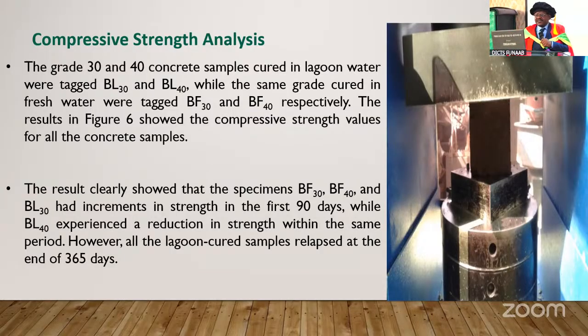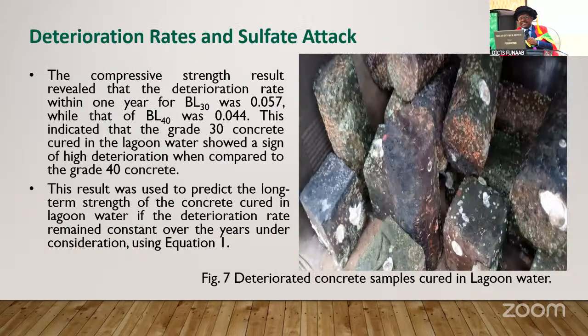Deterioration rate. The compressive strength results revealed that the deterioration rate within 1 year for BL30 was 0.057, while that of BL40 was 0.044. This indicated that the grade 30 concrete cured in the lagoon water showed a sign of higher deterioration when compared to the grade 40 concrete. This is because of the concentration of cement in it. This result was used to predict the long-term strength of the concrete cured in lagoon water if the deterioration rate remained constant over the years under consideration using equation 1.